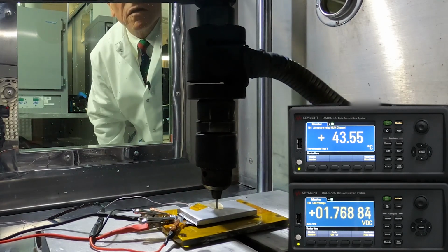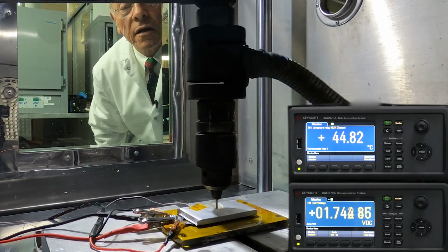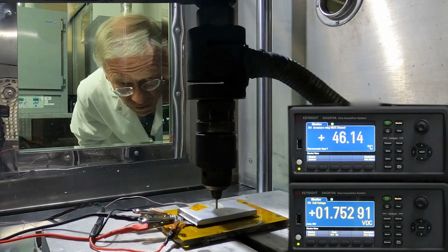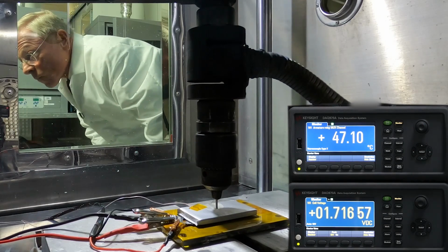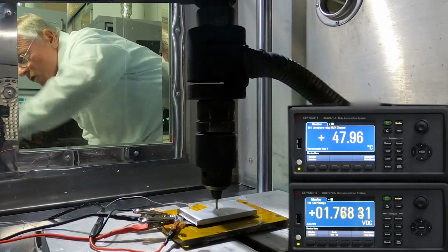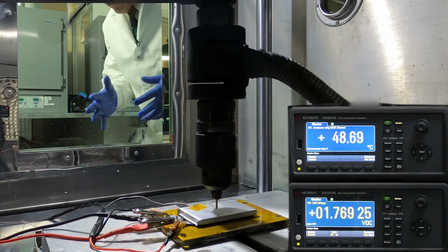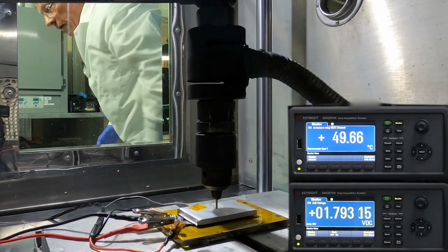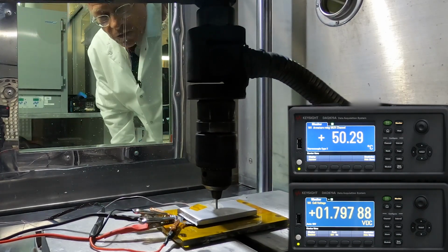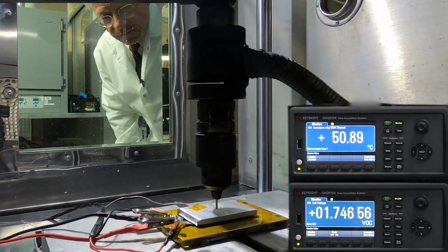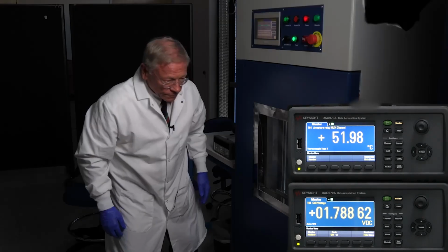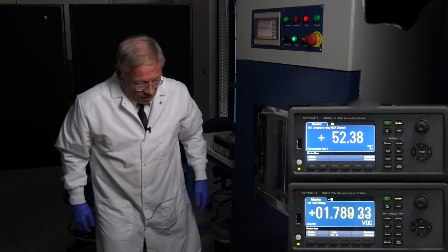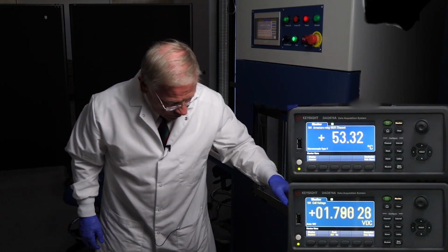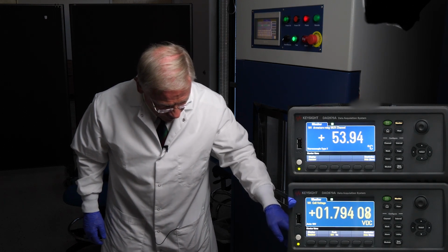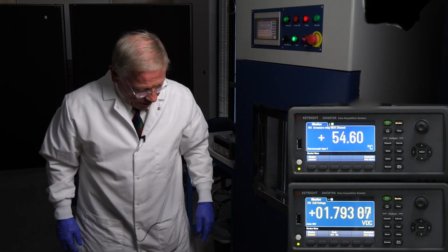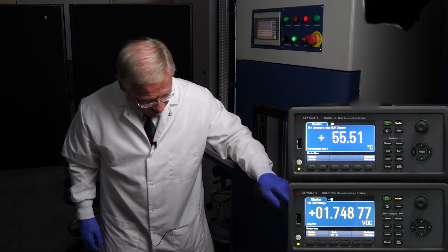I see a little bit of gas coming out. There's a little bit of swelling. Temperature's up to 47. Voltage is down to 1.7. So that battery is still a functioning battery, but we have a device which needs like 2.7 volts in order to operate. Temperature is climbing more slowly now, 53 degrees. Battery voltage is down to 1.8 volts and dropping. The rate of rise of the temperature is slowing down.